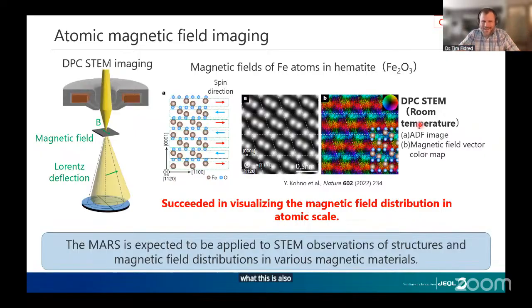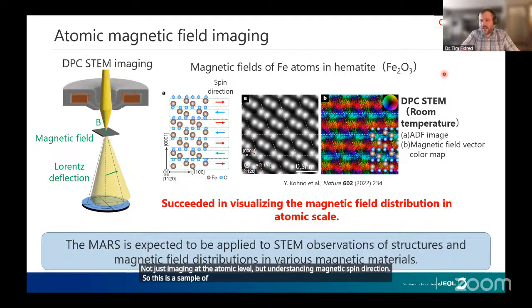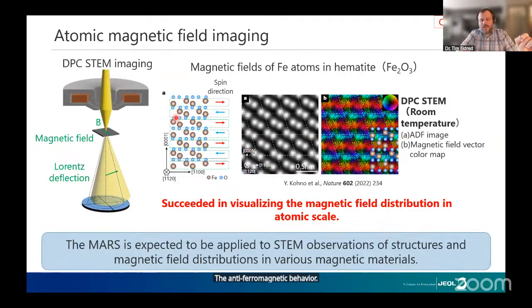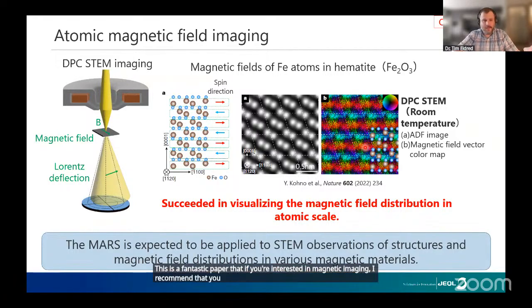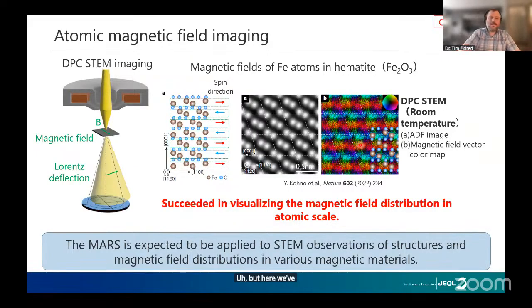What this has also unlocked is interrogation of the magnetic field that is experienced at the atomic level. Not just imaging at the atomic level, but understanding magnetic spin direction. So this is a sample of hematite, showing antiferromagnetic behavior. This is a paper by Kohno and Shibata, where they're actually able to see the magnetic spin directions on alternating layers of the hematite. This was unthinkable even 5-6 years ago. This is a fantastic paper, and if you're interested in magnetic imaging, I recommend that you take a look at this paper. But here we've again gone back to DPC.